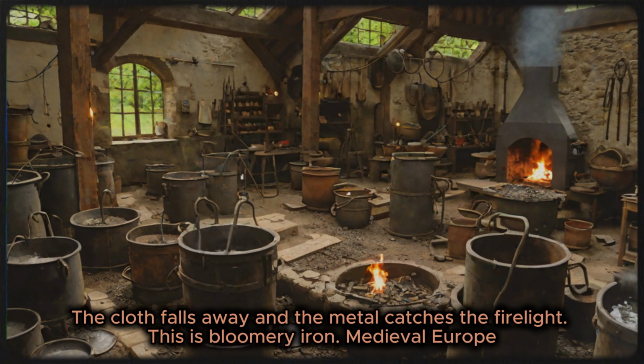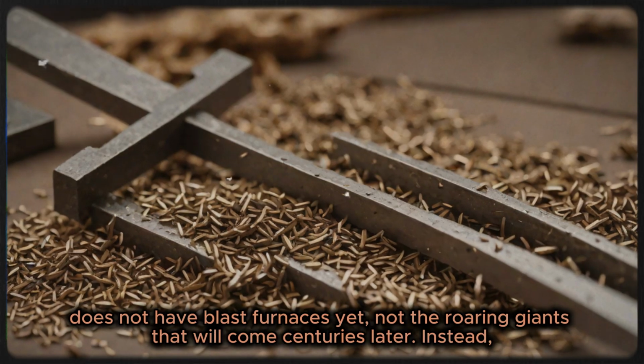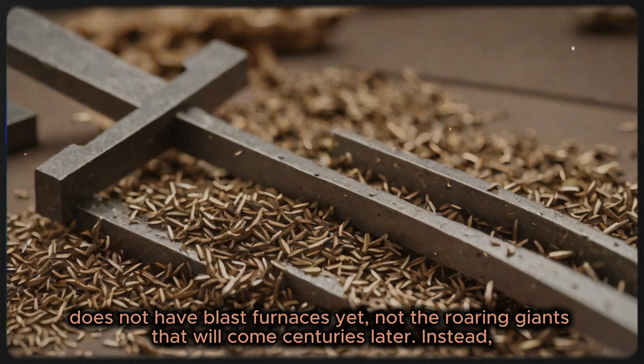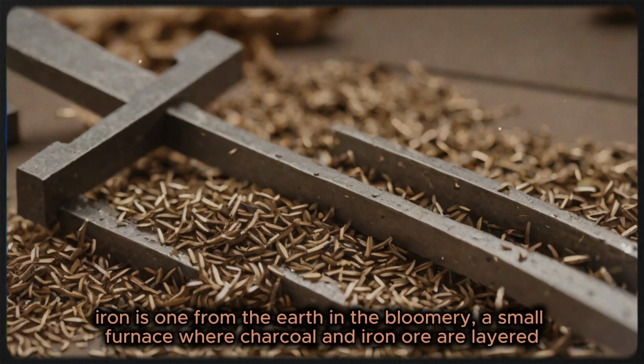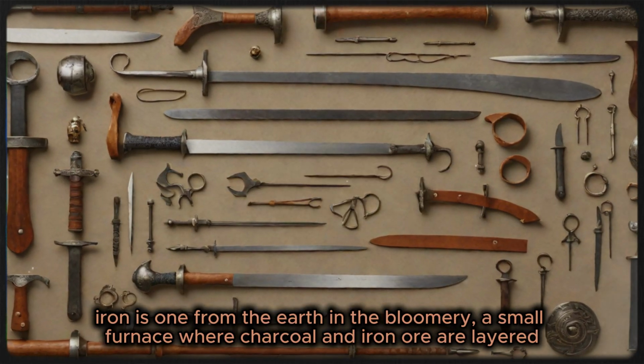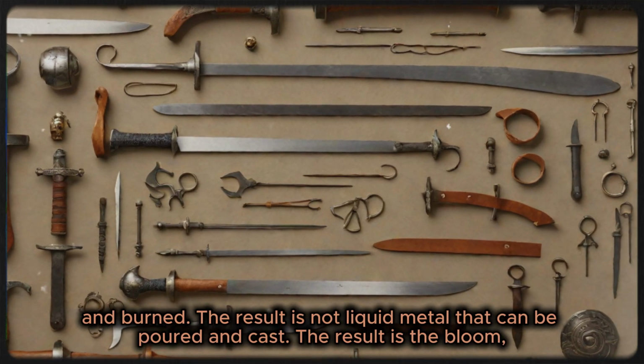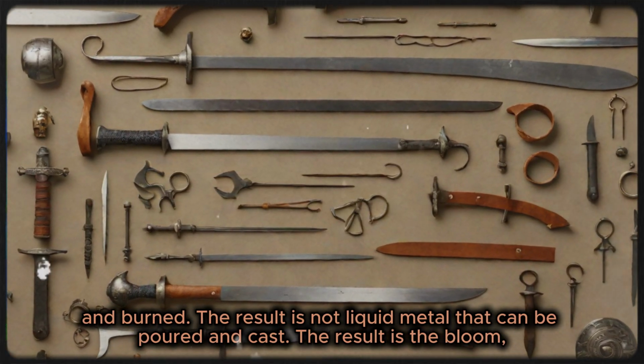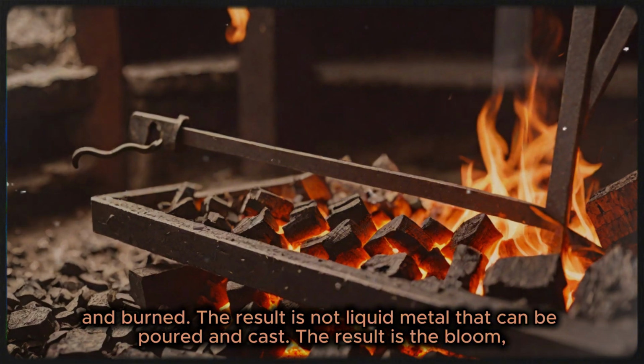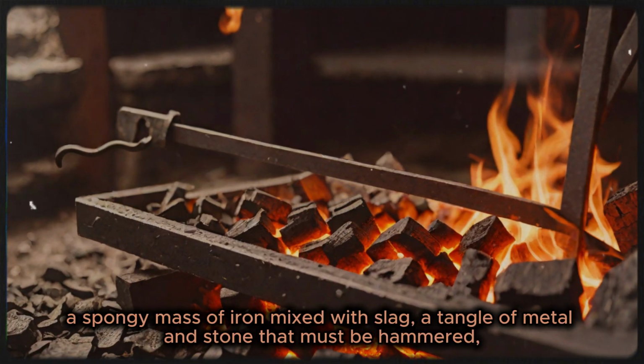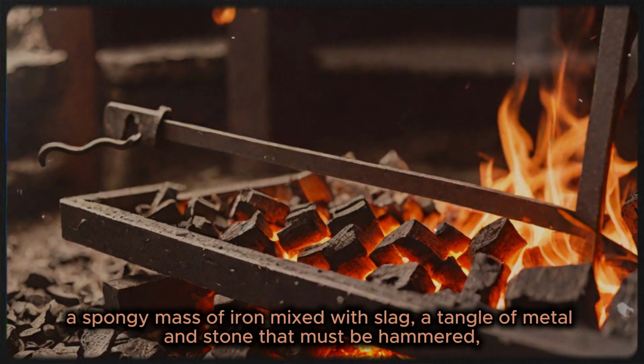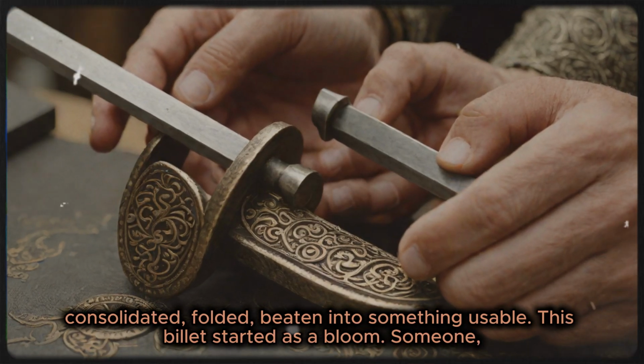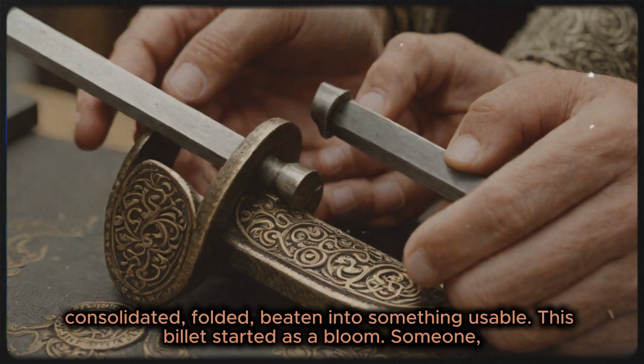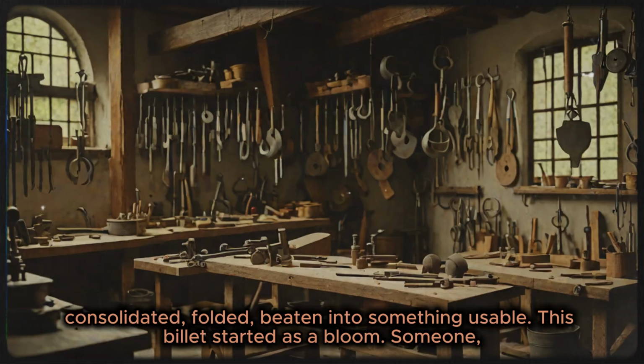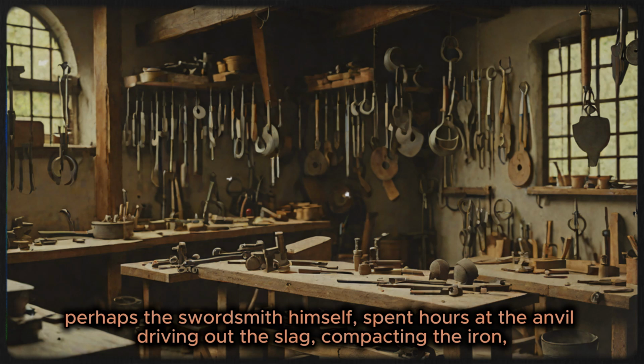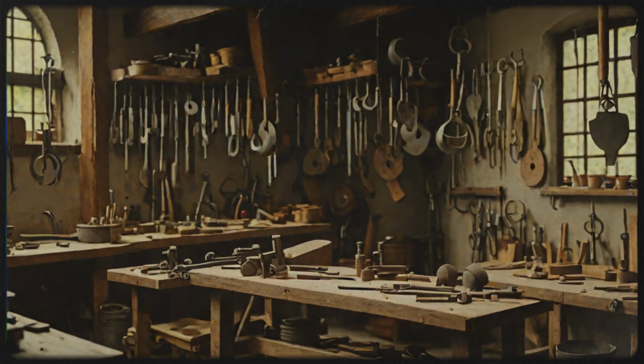This is bloomery iron. Medieval Europe does not have blast furnaces yet, not the roaring giants that will come centuries later. Instead, iron is won from the earth in the bloomery, a small furnace where charcoal and iron ore are layered and burned. The result is not liquid metal that can be poured and cast. The result is the bloom, a spongy mass of iron mixed with slag, a tangle of metal and stone that must be hammered, consolidated, folded, beaten into something usable. This billet started as a bloom. Someone, perhaps the swordsmith himself, spent hours at the anvil driving out the slag, compacting the iron, creating this bar.